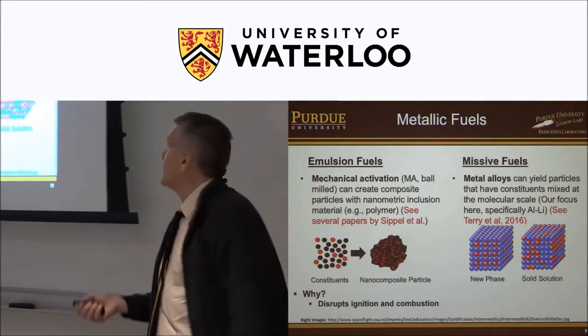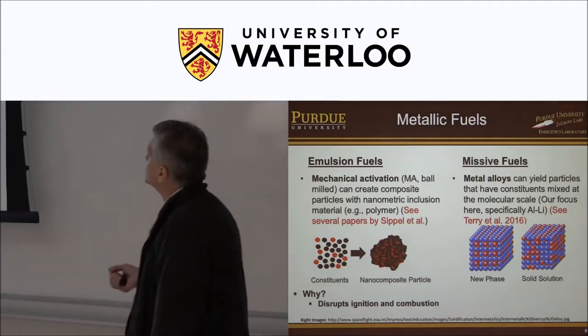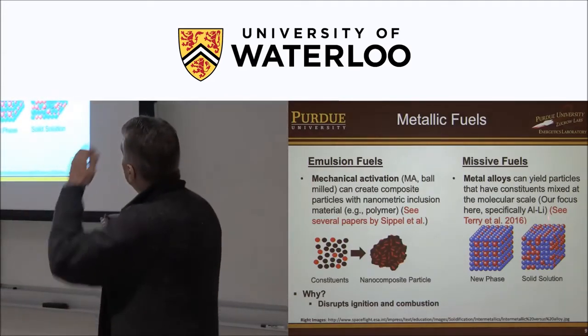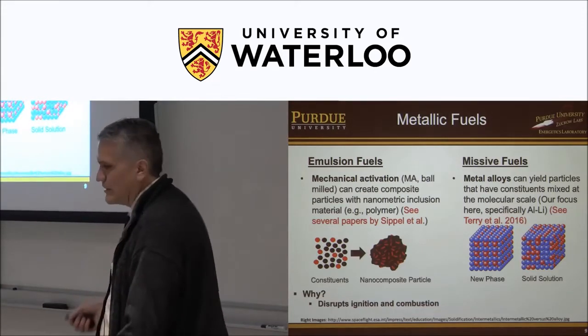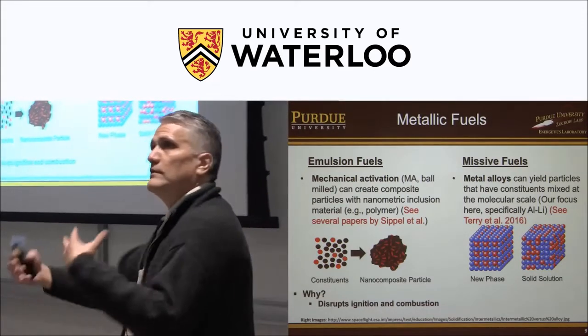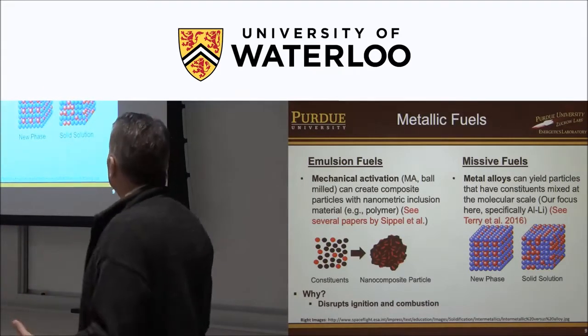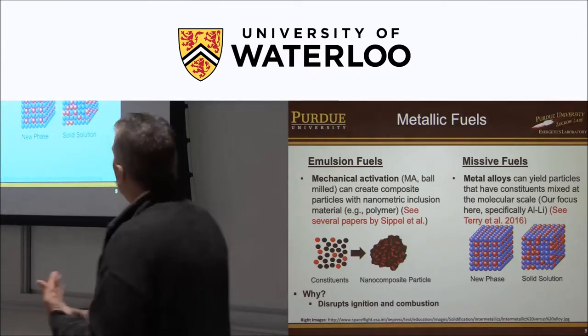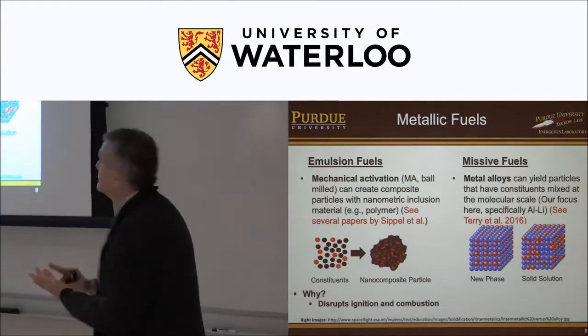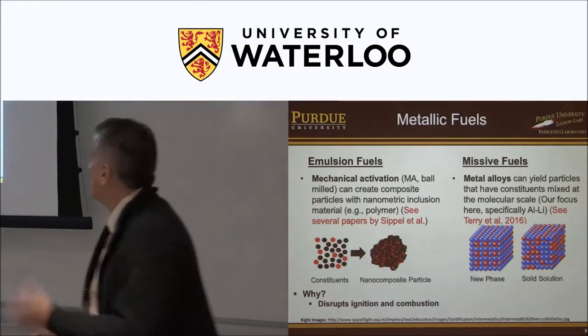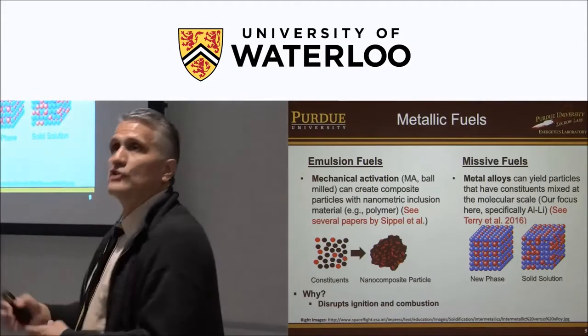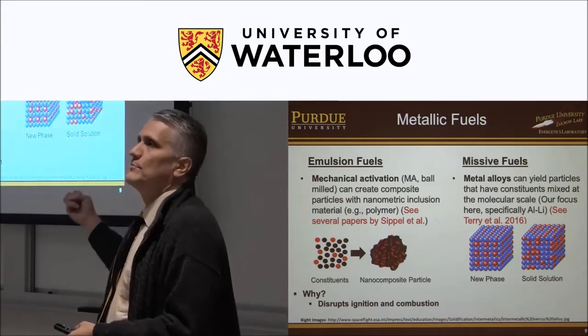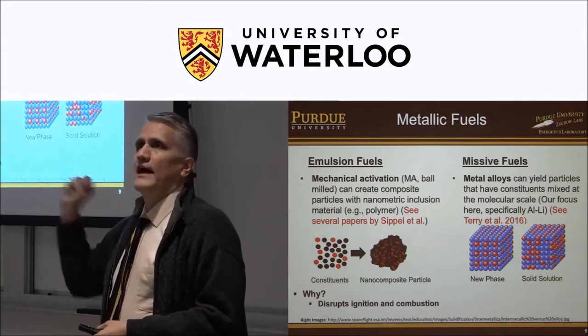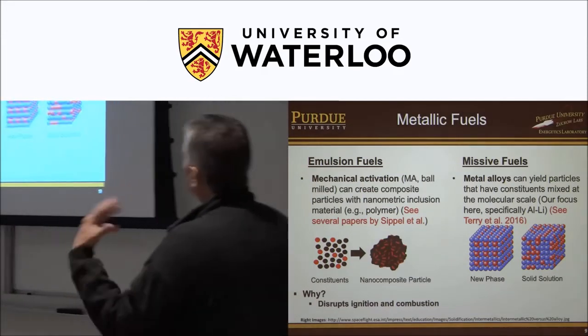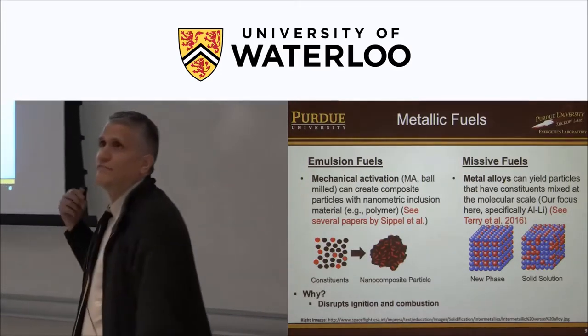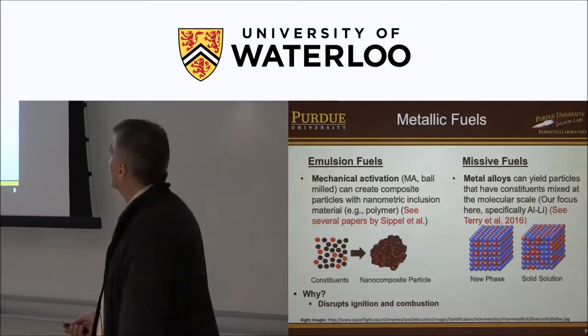Alloys are an analogy to emulsion liquid fuels, and so we've looked at, in particular, this aluminum lithium. We also looked at other alloys, but this one, the thermochemistry says, okay, look, this could be good for both cutting the HCl emission as well as performance. So I'll show that it also has the properties, because lithium is much more volatile, lower boiling point. It can micro-explode the particles into smaller droplets, and that can, very importantly, improve performance.